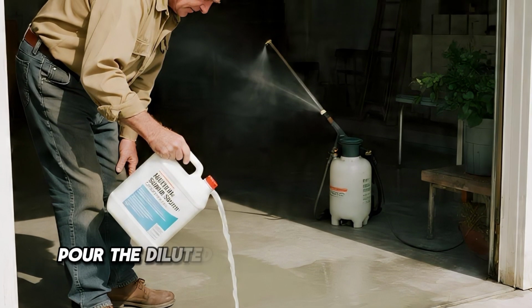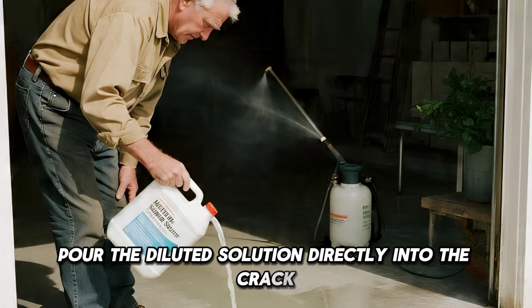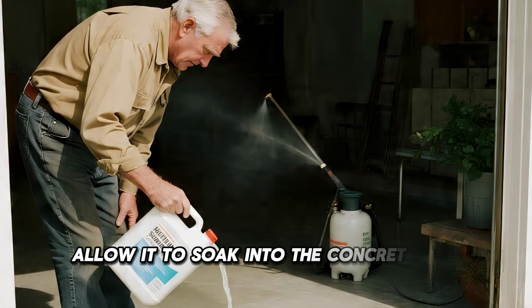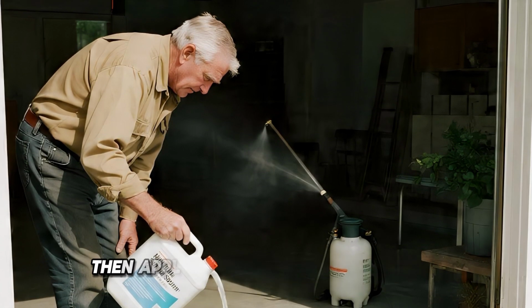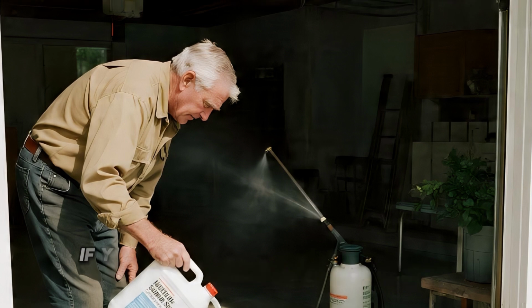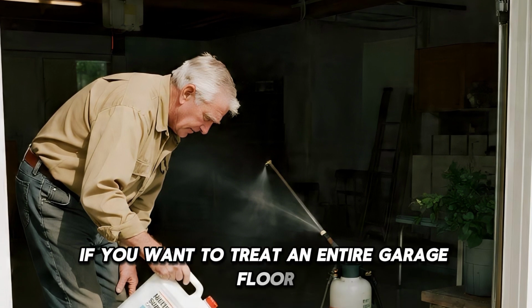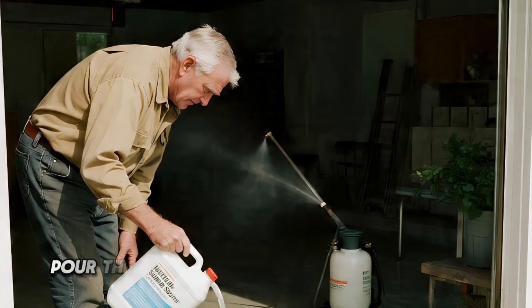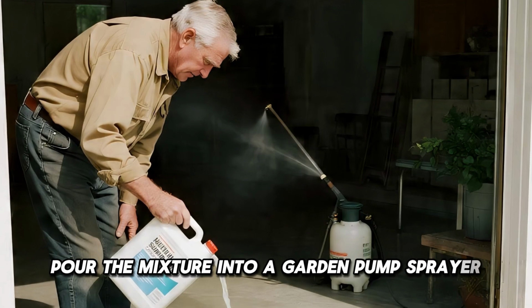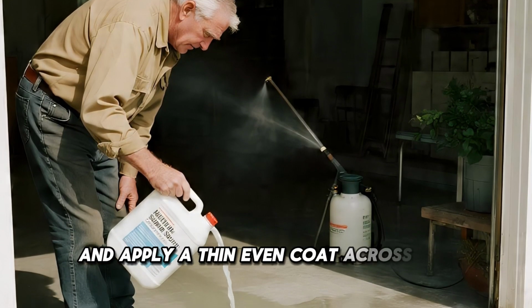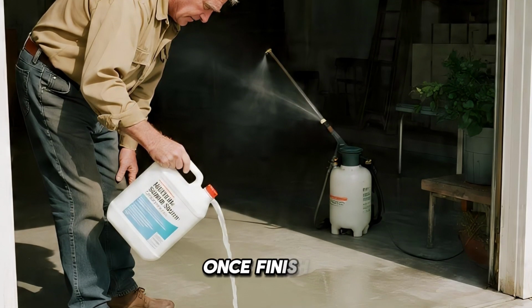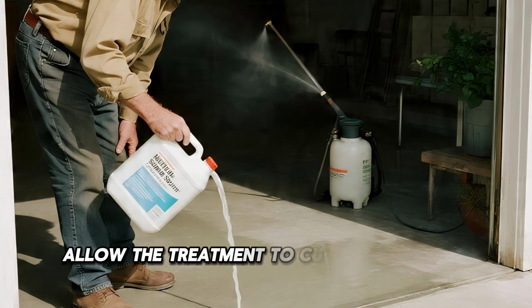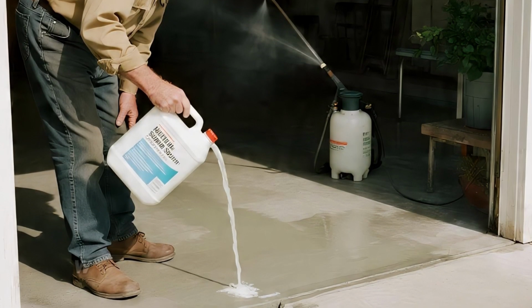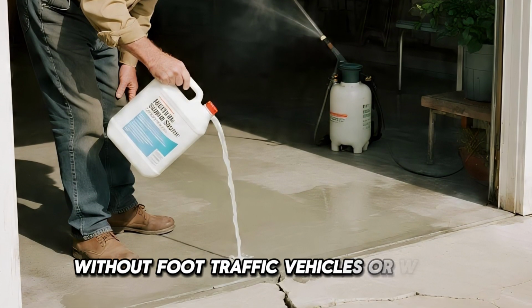Slowly pour the diluted solution directly into the crack. Allow it to soak into the concrete for about 10 minutes, then apply a second light treatment. If you want to treat an entire garage floor instead of a single crack, pour the mixture into a garden pump sprayer and apply a thin, even coat across the surface. Once finished, allow the treatment to cure for 24 to 48 hours, without foot traffic, vehicles, or water.